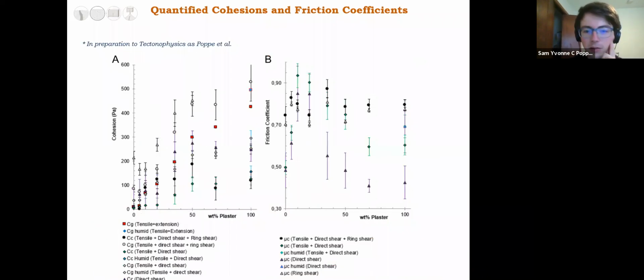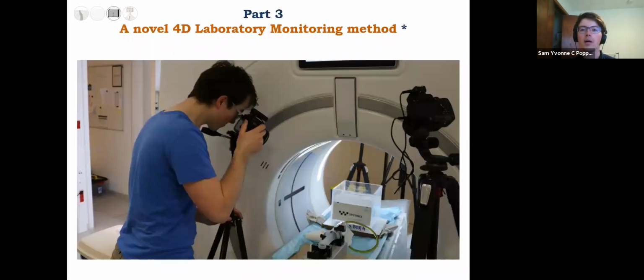And again, without further detail, what we basically found is, if you look at cohesion on your left and friction coefficient on your right, we see that as we increase the plaster content in the material, we do overall increase their strength, but at about a 35% weight percent plaster content cutoff, we move into a more complex behavior where the curved Mohr-Coulomb criterion much better describes the material than a linear Coulomb one. So as we add more and more plaster to those sand plaster mixtures, we move into more complex behavior of the material. And that was really important for us to understand how our experiments would behave.